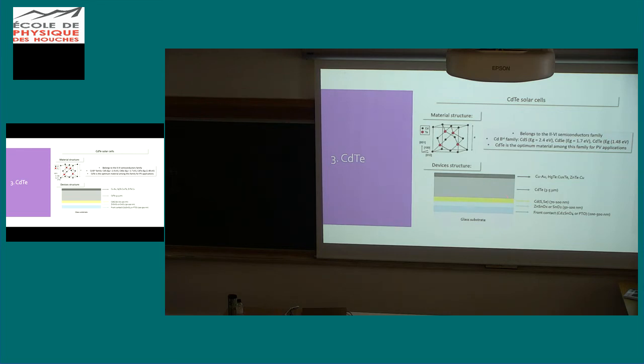You get some diffusion of sulfur and now selenium. Basically selenium is doing some front graded band gap, like in CIGS with sulfur or gallium. This was the second or third important discovery to improve the efficiency of these devices, but not improving it a lot. The problem is that you start from an amorphous material that starts to compact, so the probability of creating pinholes during this crystallization, during the growth of cadmium telluride, is quite high.